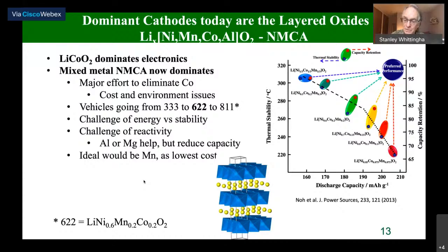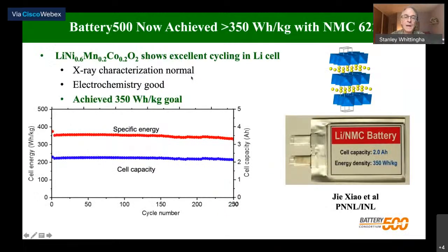Ideally, you'd like to switch to all manganese as it's the lowest cost, but there are many challenges with manganese because it has a distortion in the lattice and doesn't cycle very well. So for our Battery 500 consortium, we use the 60% nickel material. It shows excellent cycling, has very good materials properties, characterization is good, electrochemistry is good.